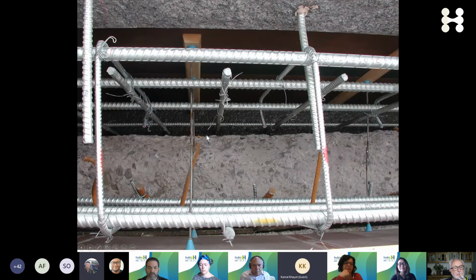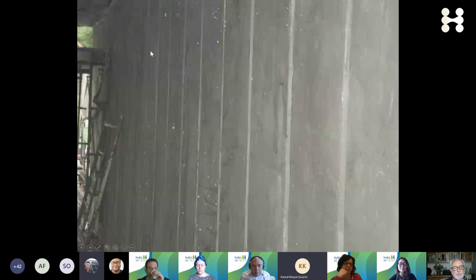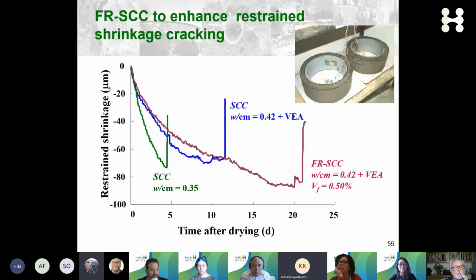And the repair looks like this. You have the existing concrete, and then there's about a section of probably 20 centimeter that is reinforced with new reinforcement that has been formed, and then you form it, and then again you are casting concrete. It adheres very well to the surface and gives you very nice surface quality, and also highly durable. This is in a Nordic area where durability is a big design issue.